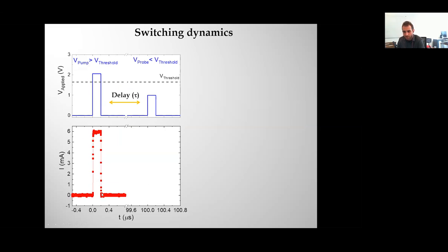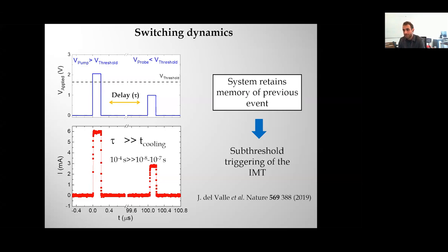You can see here the device becomes conducting. And then we wait some time and we send a second pulse. This second pulse is below the threshold, so it should not trigger the transition. But what you can see is that even after 100 microseconds, it triggers a transition. This is a pulse that is only 60% of the threshold voltage, so there is no way it should induce the transition. And this 100 microseconds is 3 to 4 orders of magnitude larger than the characteristic timescales of relaxation and cooling down that we saw. So what this shows is that the system knows that it has been fired, and it keeps a memory that it has been fired, which allows you to fire it again using much lower voltages.